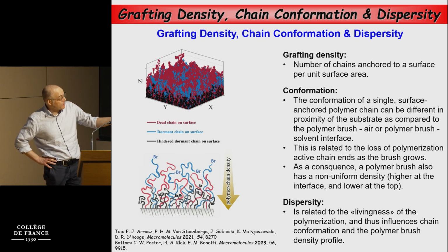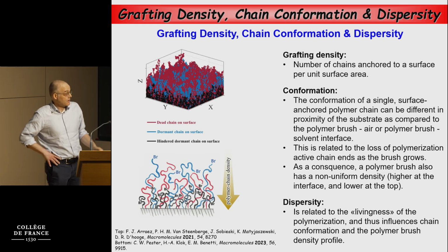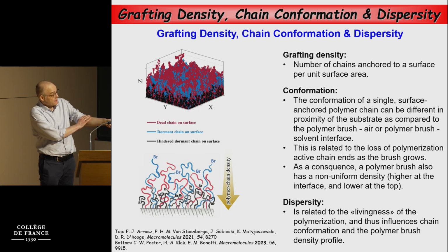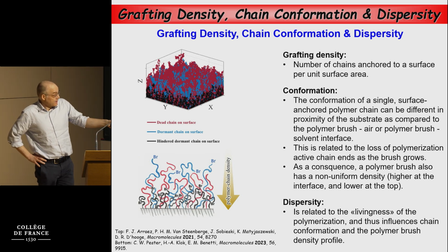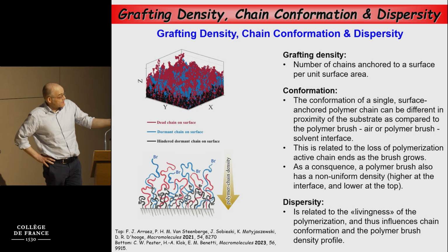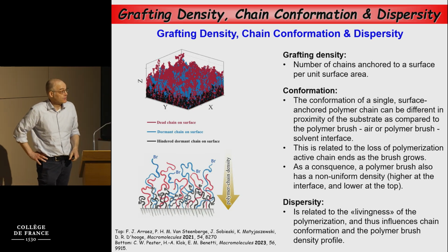So brushes are very complex systems. They are characterized by a clear non-linear decrease in polymer density as you move from the substrate-polymer interface to the polymer-air interface. There are dead chain ends buried in the polymer brush that are responsible for this. There is also termination of living chain groups that contributes to this.